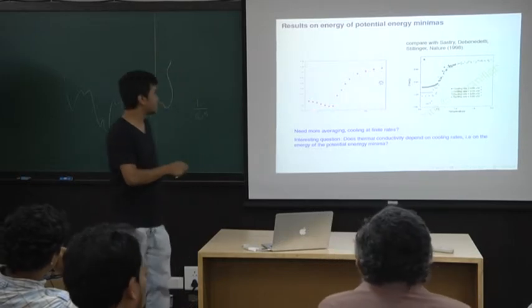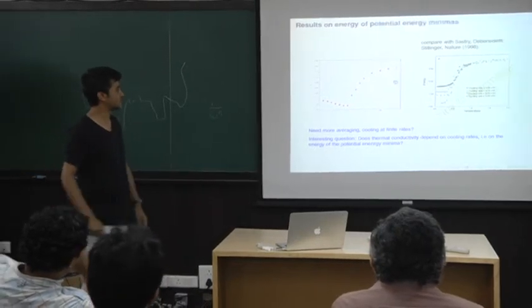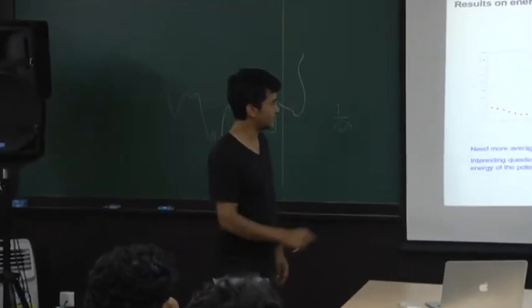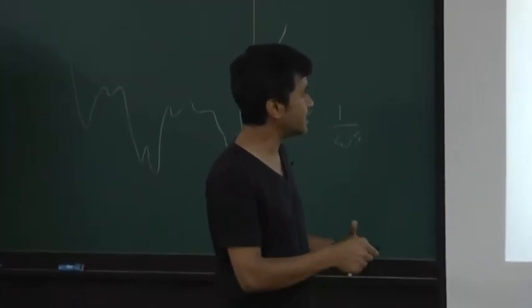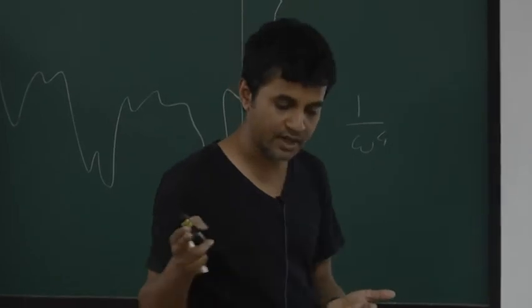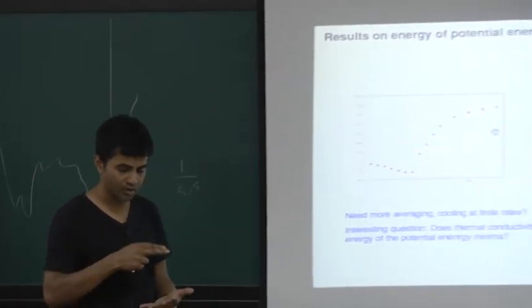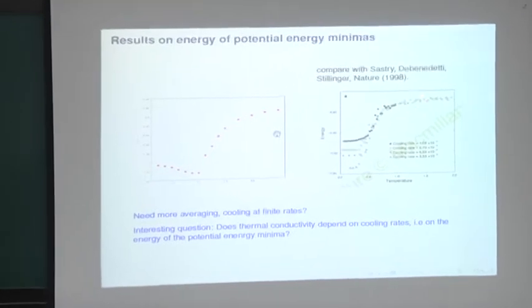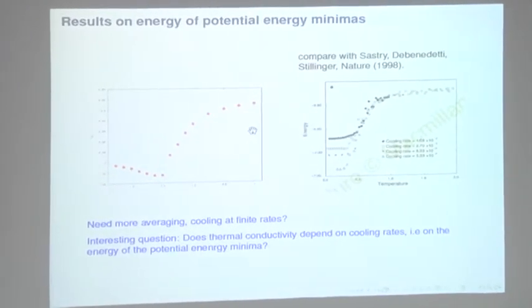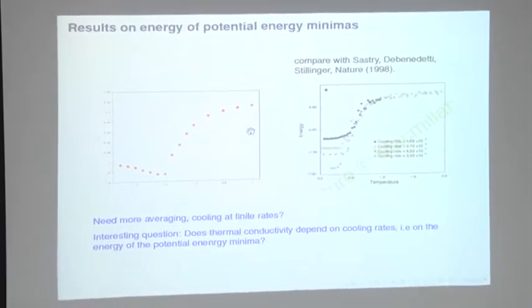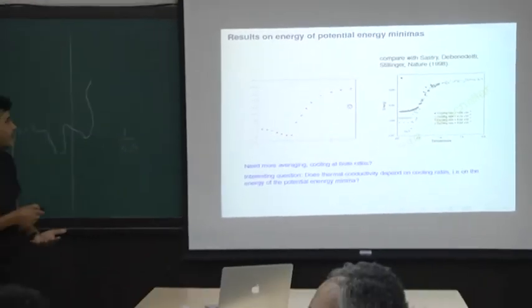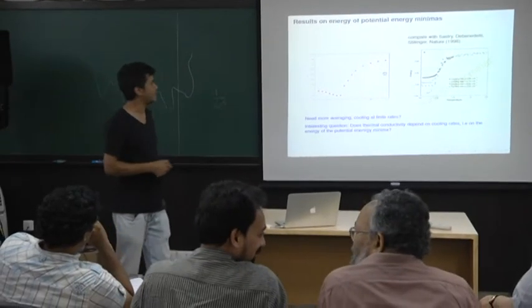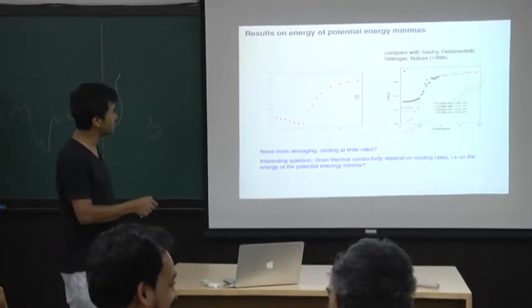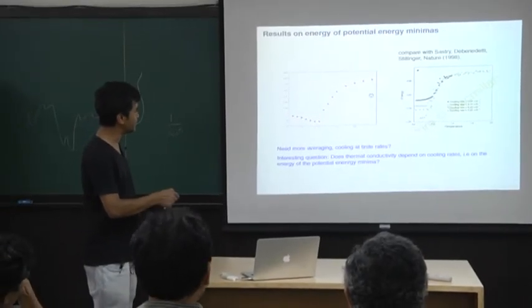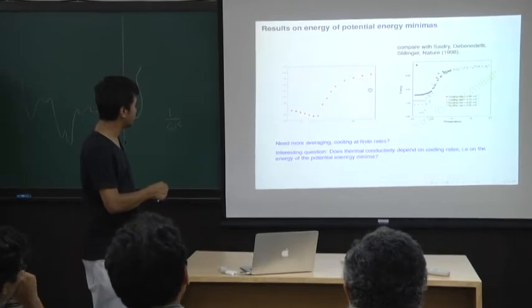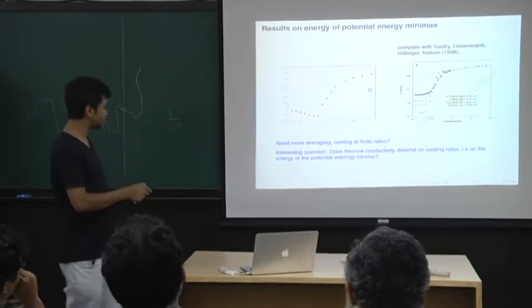You can compare this with some results that Shrikant obtained way back in '98, where he looked at the same thing, except that he was doing it at some finite cooling rate. At each temperature he was finding the corresponding energy minimum configuration, averaging over different realizations, and what he got for the fast cooling rate is something like this, which is similar to this except for this funny thing out here.